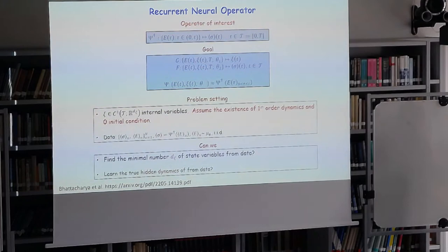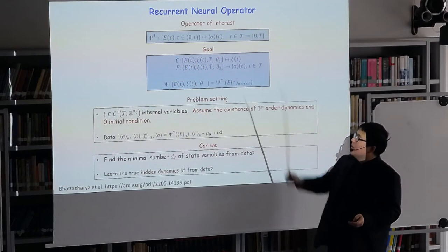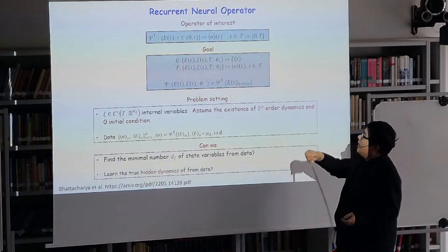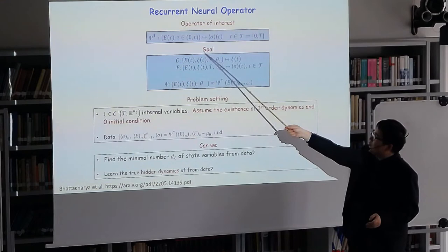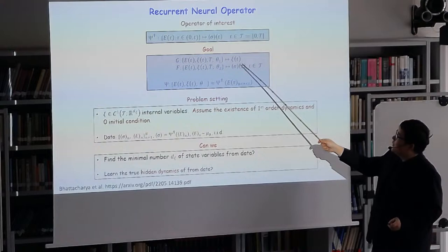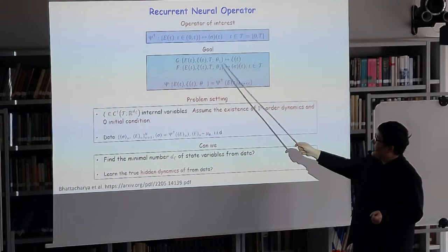It's basically a direct extension of the state internal variable theory, where we're trying to approximate this non-Markovian or path-dependent operator Ψ† using two neural networks. One is a neural operator G, which, in the problem of 1D viscoelasticity, takes the strain, the hypothesized state variable C, and the time t with parameterization, and maps to the first time derivative of C. Then we have another neural operator that takes again the strain, state variable, and time, and maps to my macroscopic output of sigma.